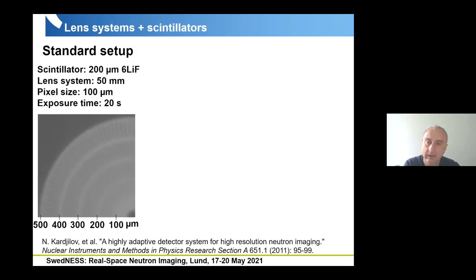Here, actually, I can show you some method development related to improvement of our detector systems, which steps we used in order to improve the resolution. So in the beginning, we started with a scintillator of thickness of 200 micrometer and pixel size of 100 micrometer. Therefore, it's not a surprise that we could achieve a resolution between 200 and 300 micrometer. Of course, here the exposure times were quite reasonable or quite good. So in 20 seconds, we had already a picture.